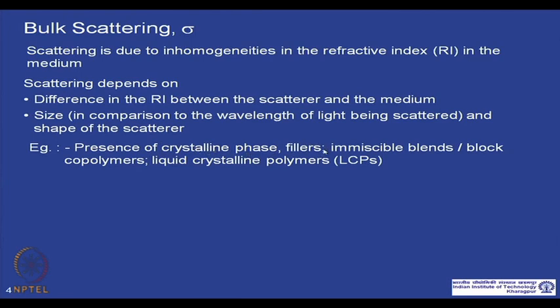If you have fillers which are of larger size, not very small, with a significant diameter, then they will scatter light. Immiscible blends or block copolymers also have a difference in refractive index between the two phases formed by the two homopolymers or two blocks, so they will also scatter. And liquid crystalline polymers, LCPs, have inhomogeneities in the refractive index.